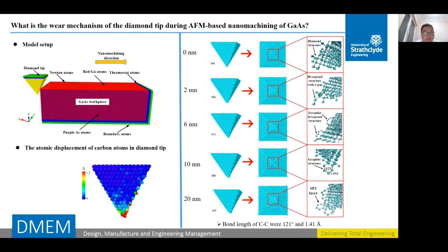Okay, on this page, it can be observed that the maximum atomic displacement of the apex of the diamond tip could reach 0.12 nanometer. This elastic to plastic deformation behavior of the diamond tip is attributed to high pressure acting on the diamond tip structure. Moreover, from the enlarged diagram of the apex of the diamond tip, it's apparent that a hexagonal structure with two carbon bond gaps forms at 2 nanometer.